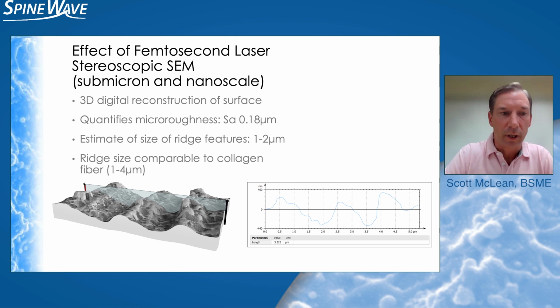Again, using a digital plane, we're able to deduce the size of those ridges and also the roughness of the texture at that scale. In this case, we estimate the size of the ridges to be between 1 and 2 microns, and that compares very well to the diameter of the collagen fibers from the literature.